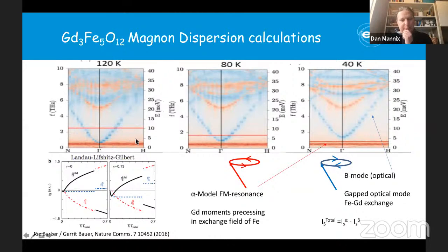It should be this interplay between these magnon modes: the lower energy alpha mode, which is the acoustic mode, and the optical mode. Because of the exchange between iron and gadolinium that increases at low temperature, this will be elevated in energy, and a gap opens up above this horizontal line, which is the thermal energy. And these modes should have opposite chirality, so opposite polarization. The magnons have a particular polarization; they precess around in one direction or the other.